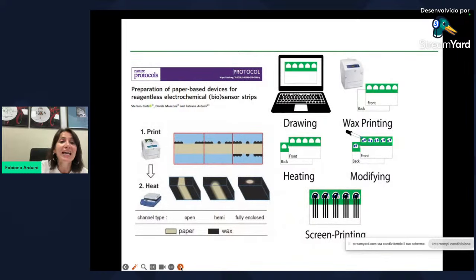So our choice was, and also is, the use of wax printing. We use wax to create hydrophobic regions, and thus to create microfluidics. In this case, we easily design the pattern. The green part is the zone in which there is the wax. Afterwards, with a wax printing machine, we print the microfluidic pattern, and then, by a heating process, meaning 1 minute in the oven, there is percolation of the wax in the paper network in order to have a 3D system. And after, we can print the electrode.